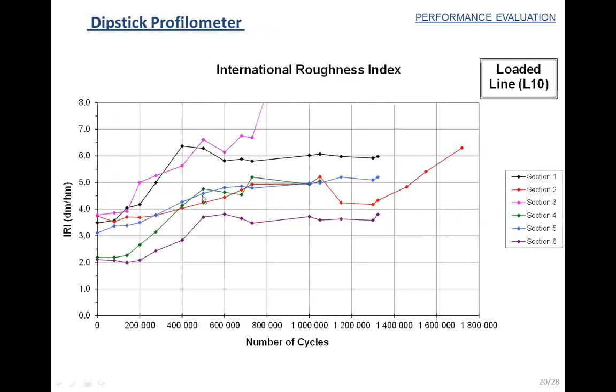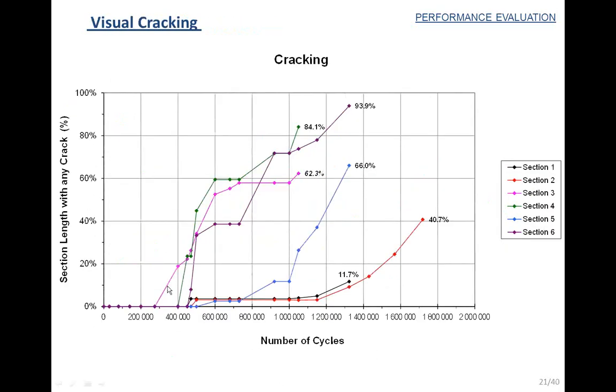Now when you see cracking, you can see that at this point when permanent deformation was very low, cracking appeared, and then cracking started to grow also. So in fact the performance of the 2 sections was very different. Section 2 had a much better performance than section 3. And in fact this was expected according to the typical fatigue law that we use for semi-rigid materials. Now, as I said, in cycle 1 million that you can see here, we finished the test for this section.